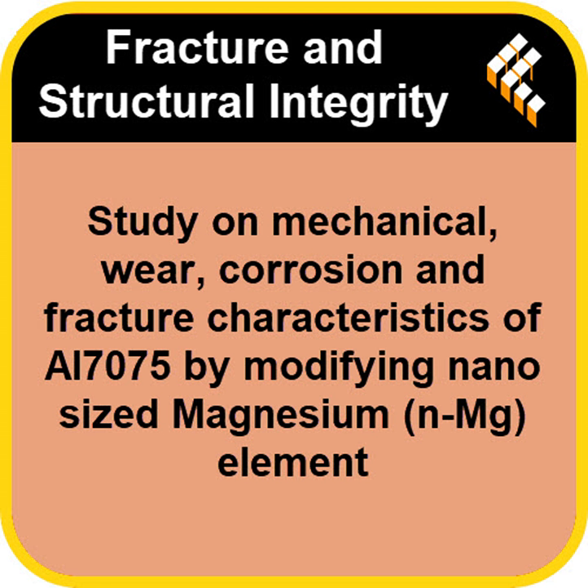Oh, okay. If you have many, many small grains instead of a few large ones, it's like trying to move a crowd through a maze full of small, intricate barriers instead of just a wide-open hallway. I like that analogy. By hindering that crowd movement, or dislocation movement, the alloy becomes inherently stronger. So that microstructural tightness sounds promising. Did it actually translate into measurable gains in strength? Oh, absolutely. Looking at hardness first, the modified alloys showed really impressive improvement. Researchers recorded a maximum hardness gain of 15.73%.